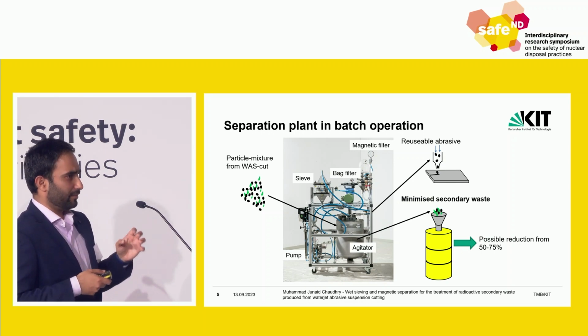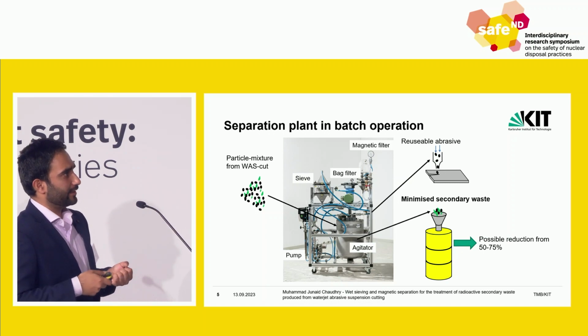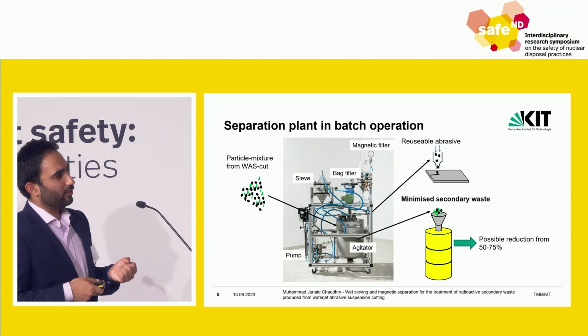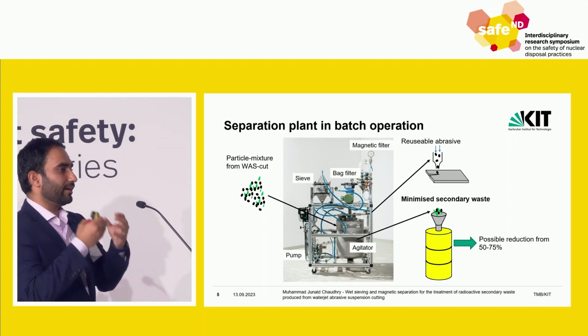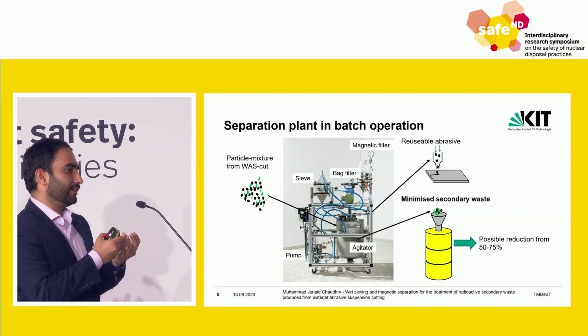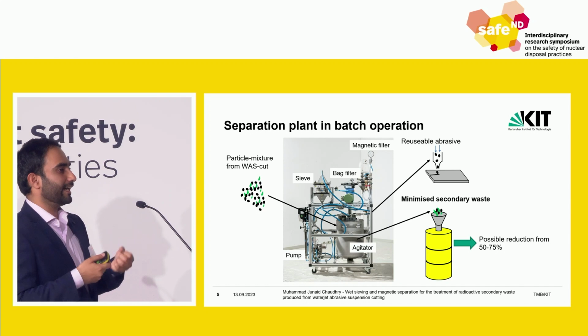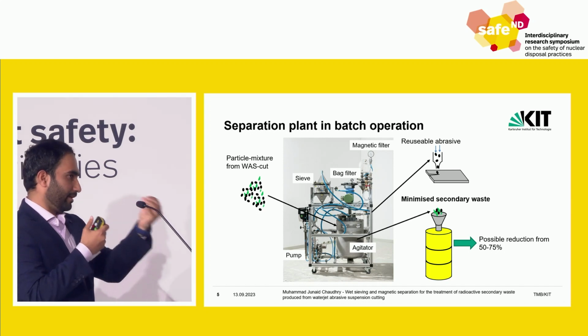From this small scale pilot plant, we normally used around 500 to 600 grams of sample material to test our plant. In the end, there was a reduction from 50 to 75% of the material that was reusable for the next cut, and it was 99.9% pure.